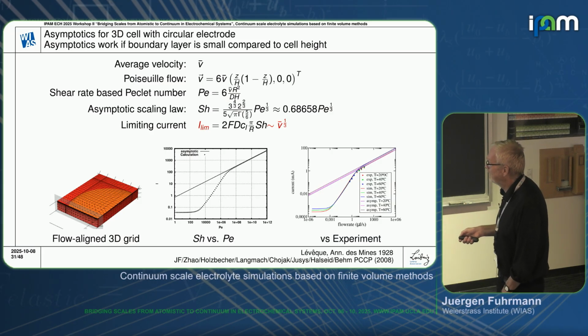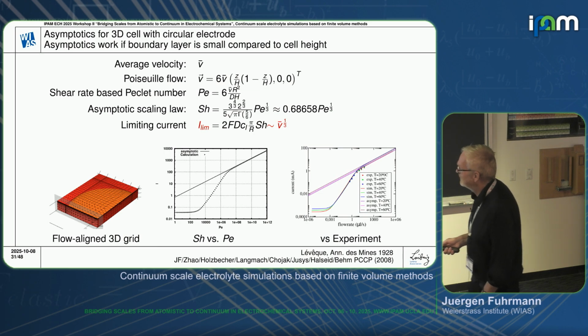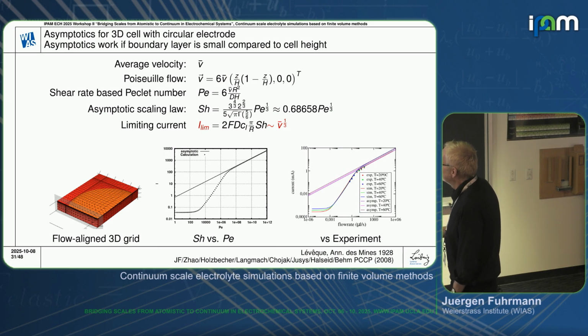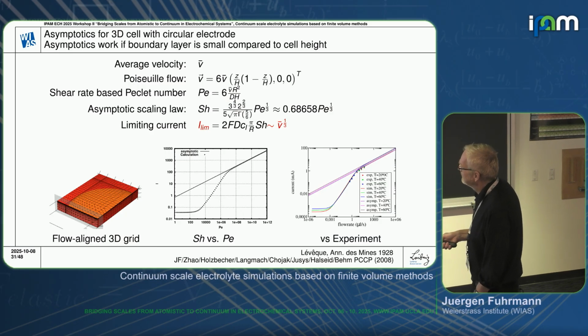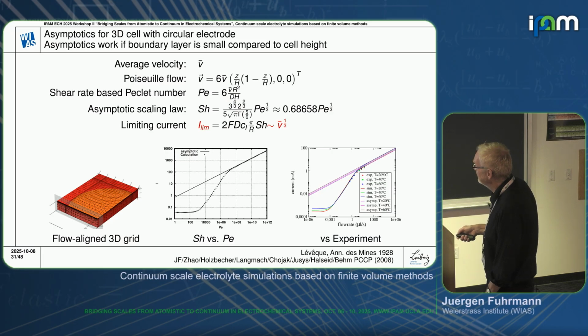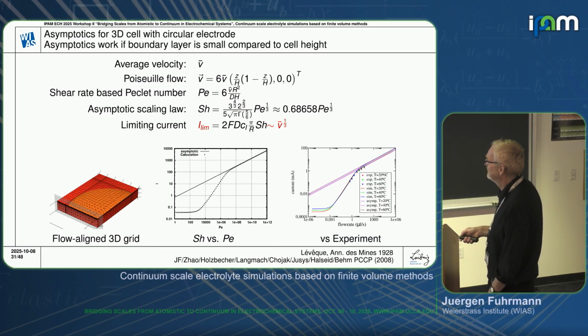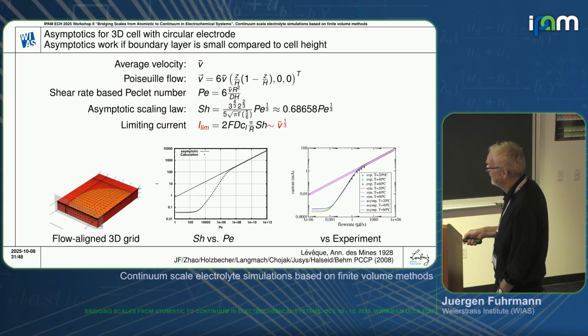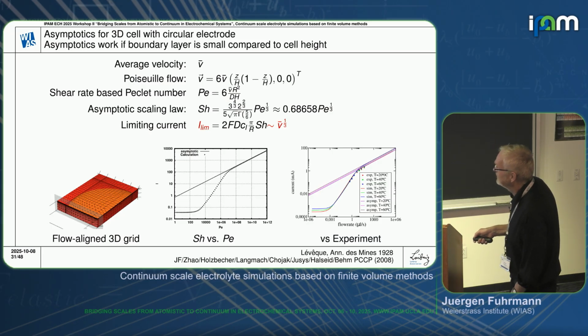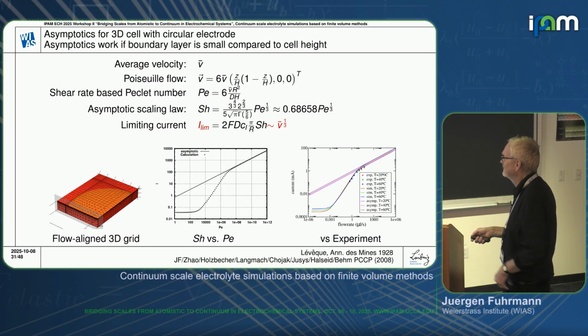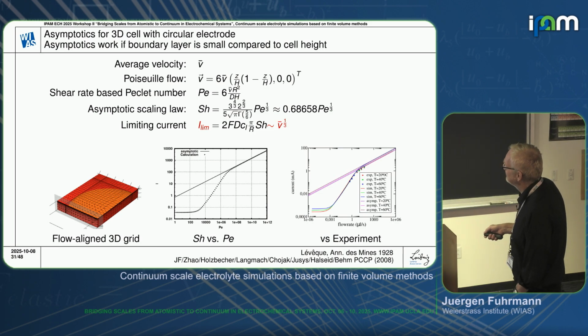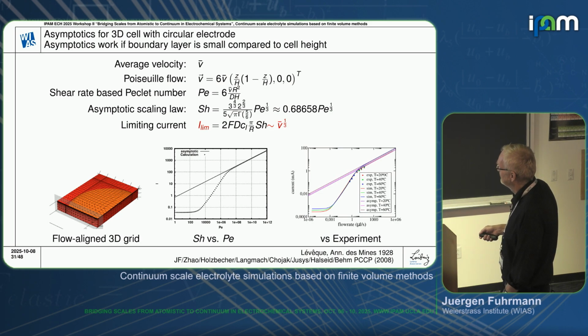And when we compare to these experimental values, we see that these are log-log plots of the Sherwood number, which is proportional to the current. So the straight lines give the asymptotic values, but we see that we have deviation for smaller Peclet numbers from these asymptotic values. And this means that, in fact, the cell height correlates with the size of the hydrodynamic boundary layer. So, and that was important when we tried to interpret these measurements, part of the measured values basically lie in the subasymptotic part.